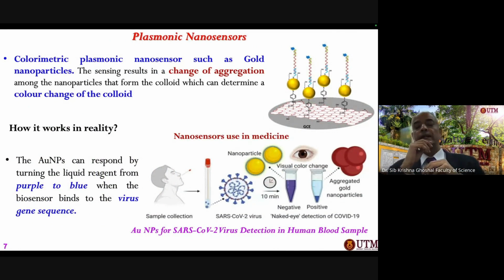Now, if we use these nanoparticles for different kinds of sensing, one such sensor we have recently noticed is that gold nanoparticles have been used heavily in COVID detection. Just by changing the color of the solution, if you put the nasal or throat discharge in, it changes from purple to blue color, and that is the way we could detect the coronavirus as positive or negative. So these self-aggregations of gold plasmonic nanoparticles can be used for detection of virus, bacteria, microbes, protozoa, amoeboids.